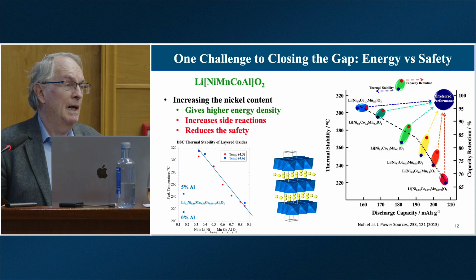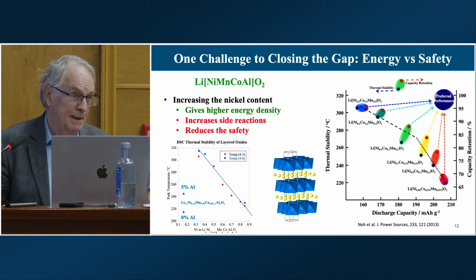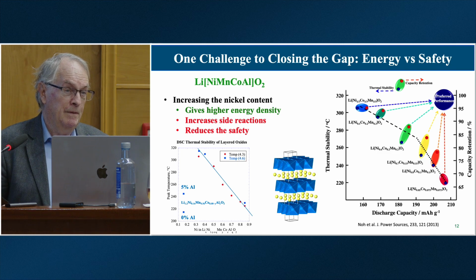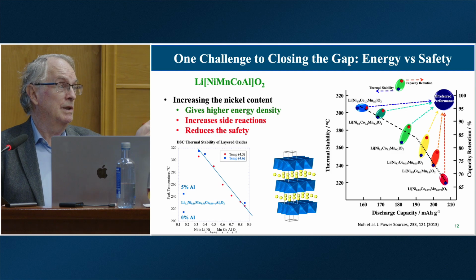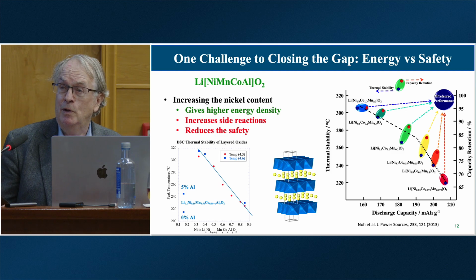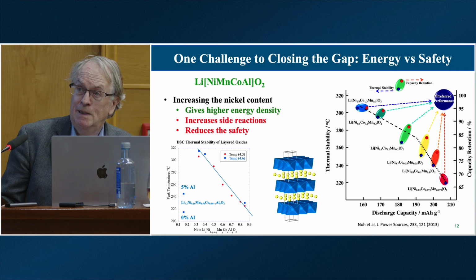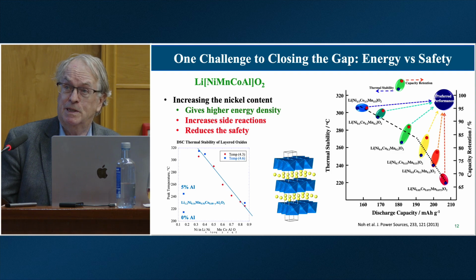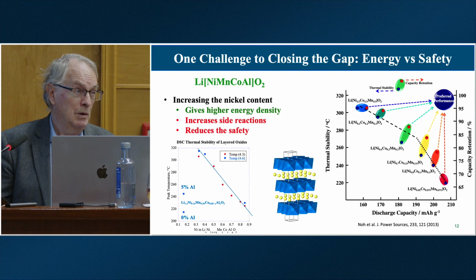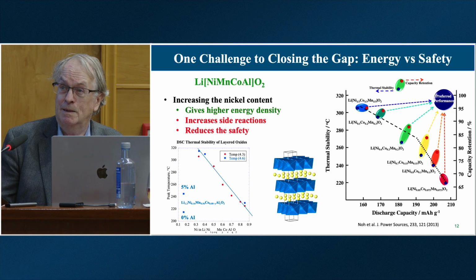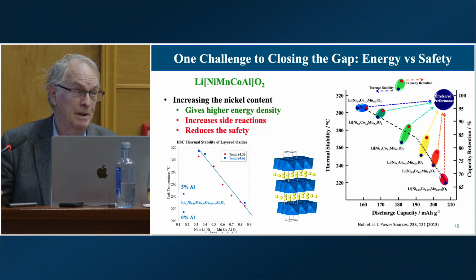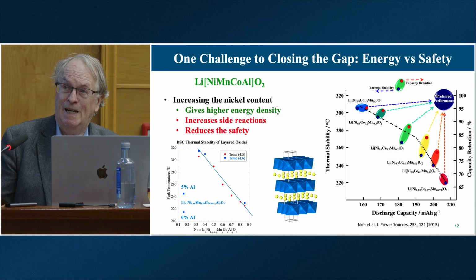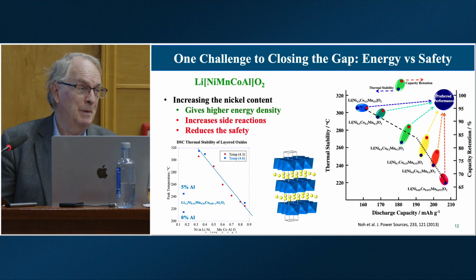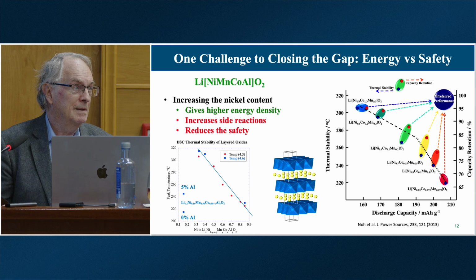So how do we get higher? First thing we have to do, as I mentioned, we want to get the cobalt out, but the other big advantage of getting the cobalt out, we can increase the nickel content. And if you look at the bottom of that plot there, which shows the discharge capacity as a function of the nickel content, you can see the discharge capacity goes up with the nickel content. But you also see now looking at the left axis that the thermal stability of these materials goes down drastically as we increase the nickel content.